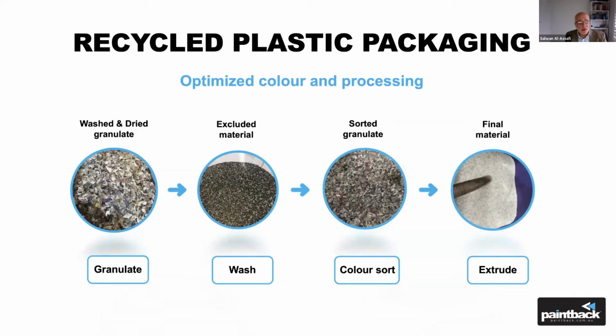So the process is first to get the shred granulated, wash it, get the excluded material out. So that's all the dark, for example, you can see here under the excluded material, that's all dark plastic that is not suitable for this particular product. We have to remove it. And then we go through the color sorting, polymer sorting, and then after extrusion, we end up with the final material, which is bead.